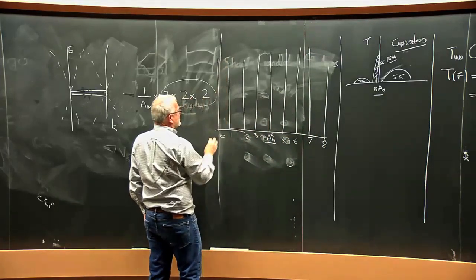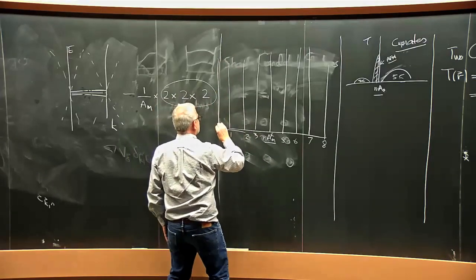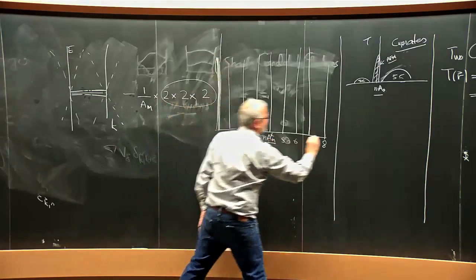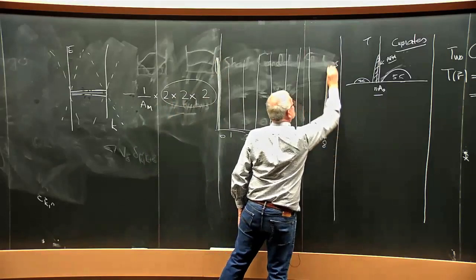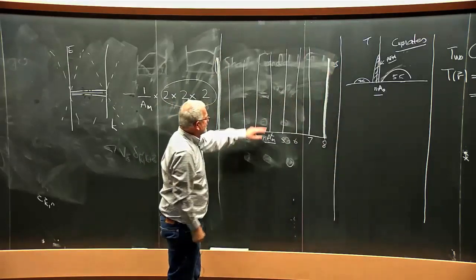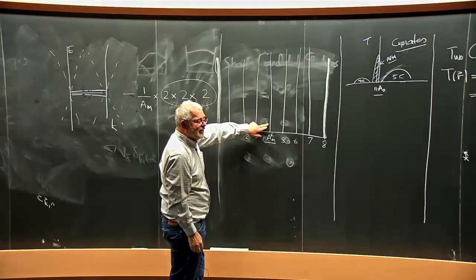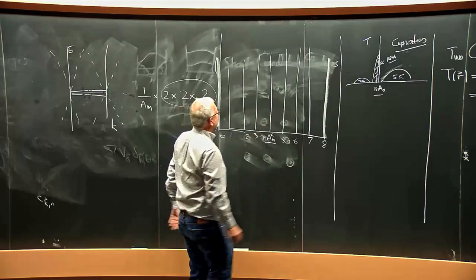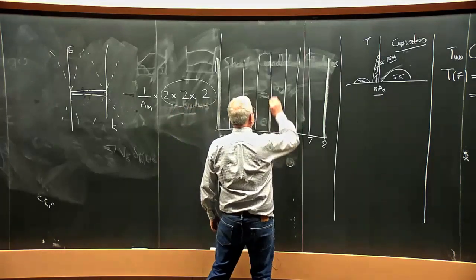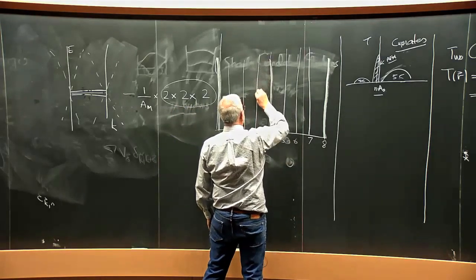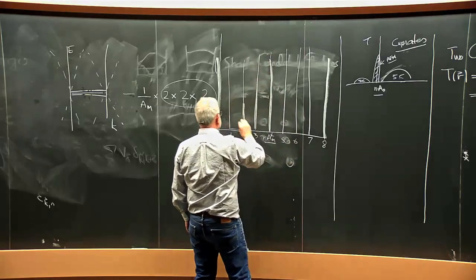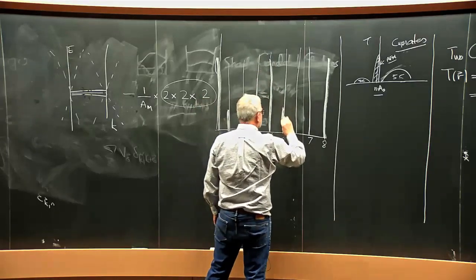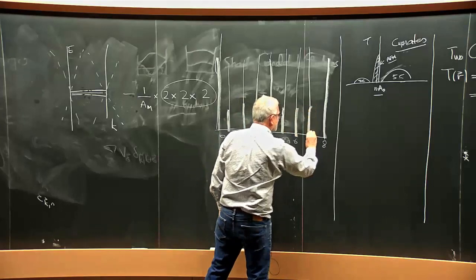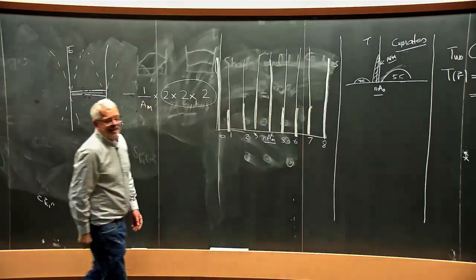Okay, and so it turns out that there are band insulators at these points. This is the empty band, the Moiré band. In the Hubbard case, when this band was half filled, there was an insulating state. And here there is also. And it appears that as the samples get better and better, insulating states are emerging at all integer numbers of electrons per Moiré. And then, bingo!